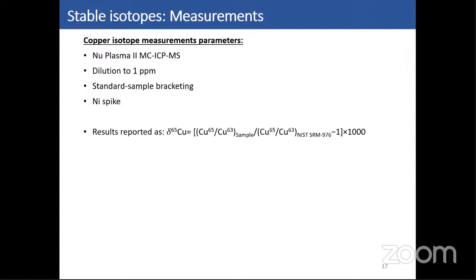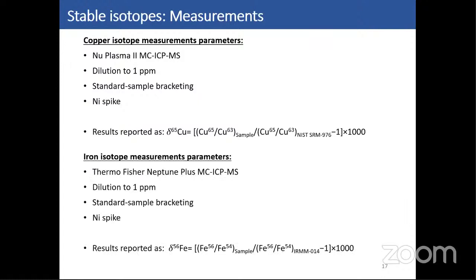Copper isotopes have been measured on a Nu Plasma II multi-collector at UJ with the help of Henriette Öckermann. The fractions have been diluted to 1 ppm and spiked with a nickel solution and measured with the standard sample bracketing method, which consists of successive measurements of standard and sample, to correct the mass bias which occurs during the measurement session. Iron isotopes have been measured on the Thermo Fisher Neptune Plus multi-collector, with exactly the same parameters at 1 ppm with nickel spike and standard sample bracketing, but in Lyon at the ENS CNRS in France.